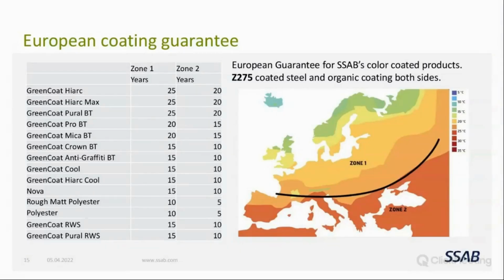This Green Coat European coating guarantee is divided into zones. Zone 1 gives a maximum of 25 to 15 guarantee years depending on the color coating, and zone 2 gives a maximum of 20 to 10 guarantee years depending on the coating. So for example, GreenCoat Hiarc and GreenCoat Pural BT, 25 years in zone 1 and 20 years in zone 2. The boundary of the zones is roughly the 45th latitude, and the minimum zinc quantity must be 275 grams per square meter in the separate steel material, so that the guarantee is valid.